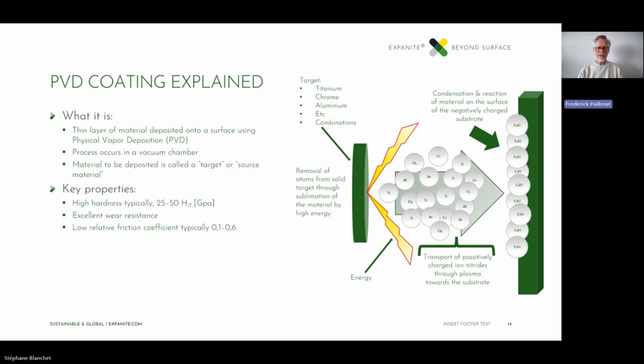You ignite a spark on the surface of the target, and through magnetic coils you get this flash, if you will, to jump around on top of this surface, bringing high energy in certain points to the surface of the material, actually sublimating the metal, where the gas is shot out into the chamber, where it's met with a plasma. The plasma consists of different gases, where you take nitrogen from. The atoms from the target will then combine with the nitrogen, forming nitrides.